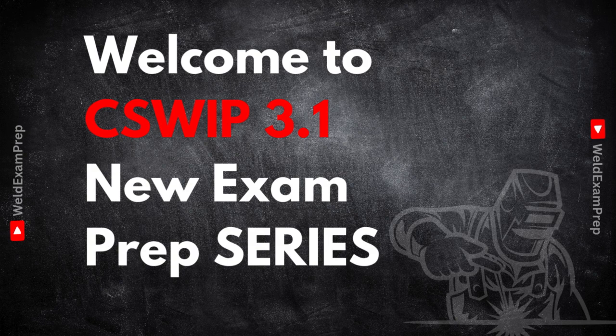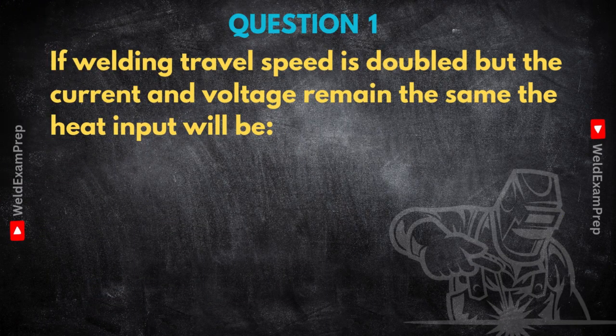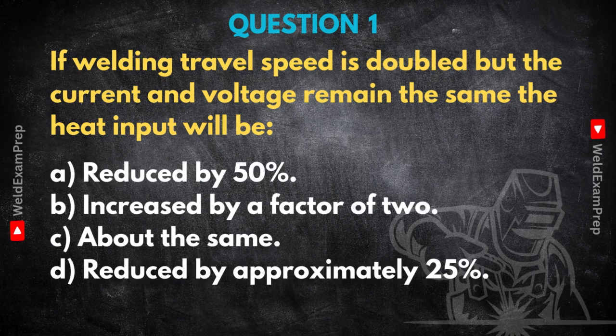Imagine you're on the shop floor, maybe watching a weld on some critical structure. Now, if the welding travel speed is doubled, but the current and voltage stay exactly the same, what happens to the heat input? Your options are A, reduced by 50%, B, increased by a factor of 2, C, about the same, or D, reduced by approximately 25%. This is a fundamental one, and the physics points very clearly here. The correct answer is A, reduced by 50%.